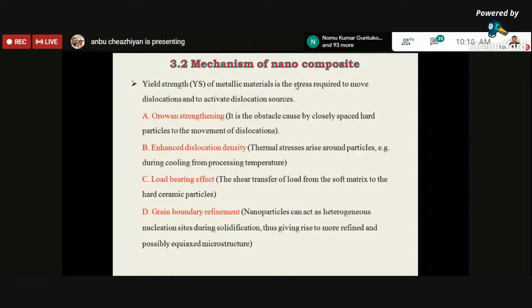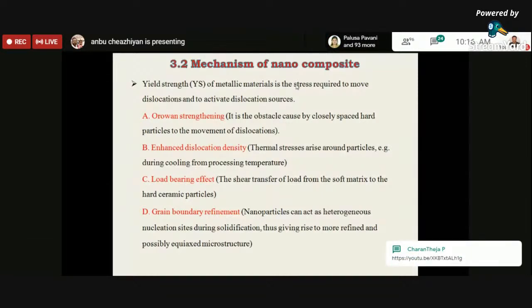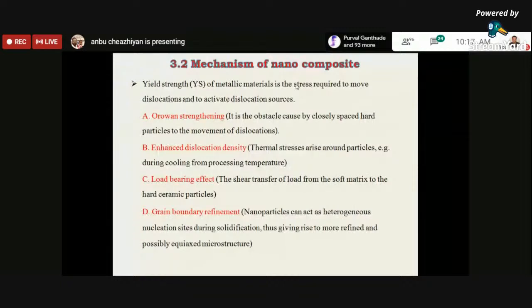Next, we go for the load bearing effect: the shear transfer of load from the soft matrix to the hard ceramic materials. The reinforcement mechanism is effective only with coherence. Finally we go for grain boundary refinement. Nanoparticles act as heterogeneous nucleation sites during solidification, giving rise to a more refined, possibly equiaxed structure. In addition, the nanoparticles restrict the migration of thermally excited grain boundaries due to pinning effects during recrystallization. These were the general strengthening mechanisms of nanocomposites.